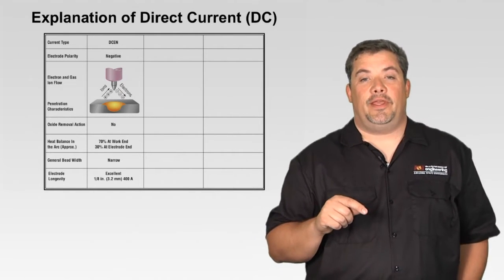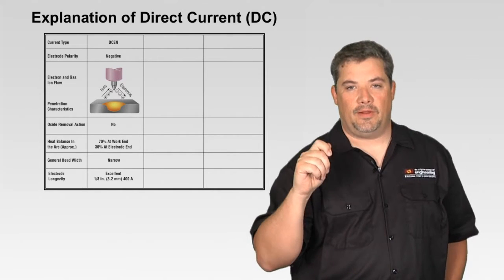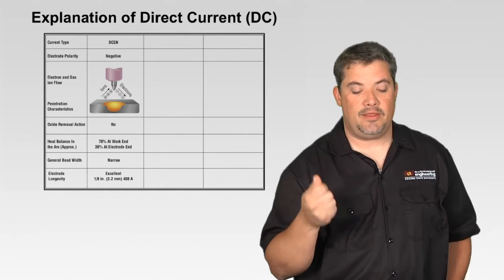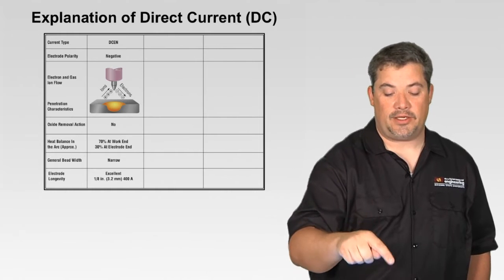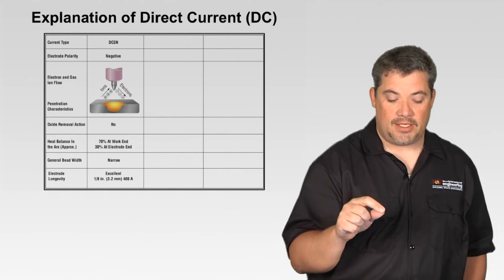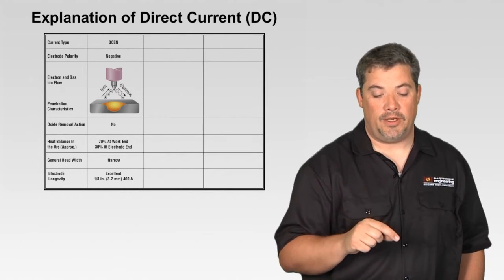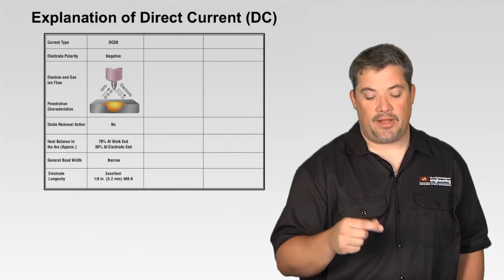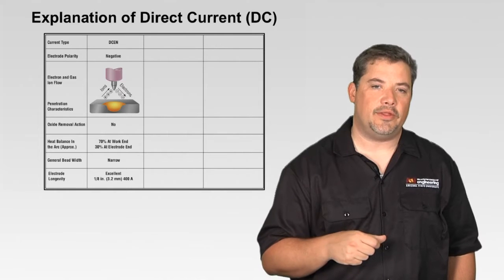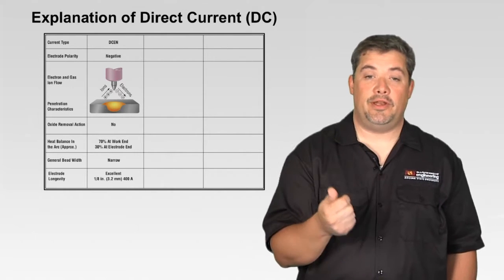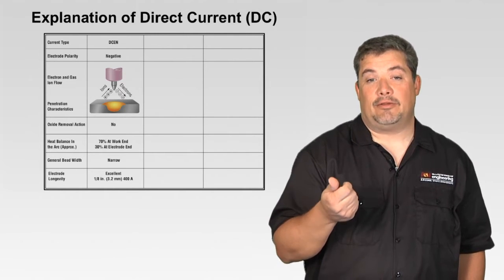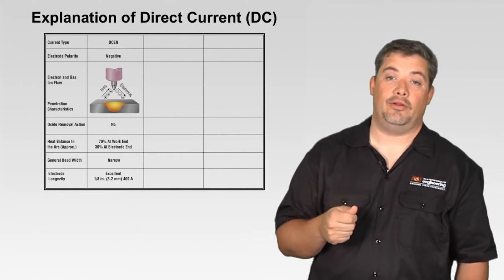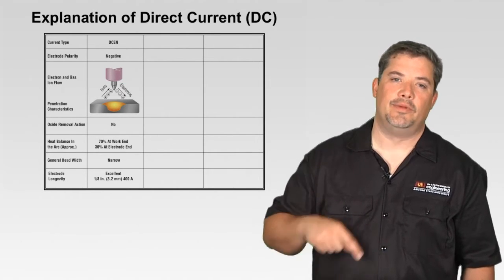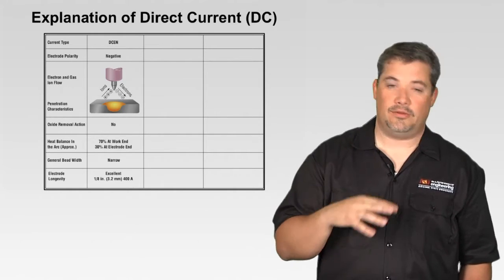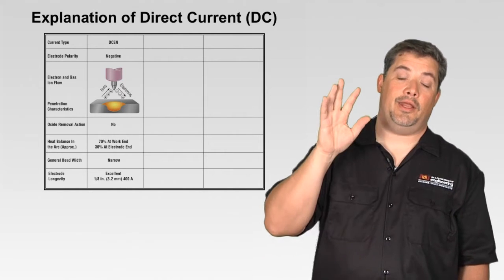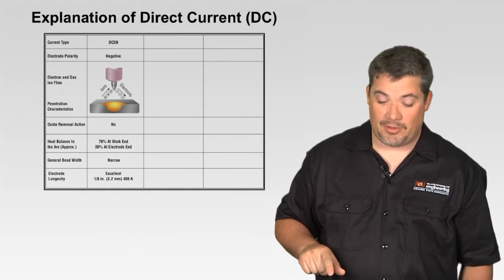So this chart that we're going to start filling in, you're going to want to pay attention when we get this third column filled in. Direct current electrode negative is the key that we use for all metals. We say that electrons flow from negative to positive. In this case, the oxide removal action we'll be talking about later doesn't happen in DC electrode negative. The heat balance is about 70% of the heat on the work and about 30% on the tungsten. So the general bead width is narrow, and the tungsten capacity or longevity is great. A 1/8 inch tungsten will carry 400 amps with direct current electrode negative. This is great for welding everything but aluminum and magnesium. I can do aluminum, there are ways, and it works. Just like in all welding, there are 10 ways to skin the cat, but some things are just better than others, and in this case, electrode negative is great for everything.